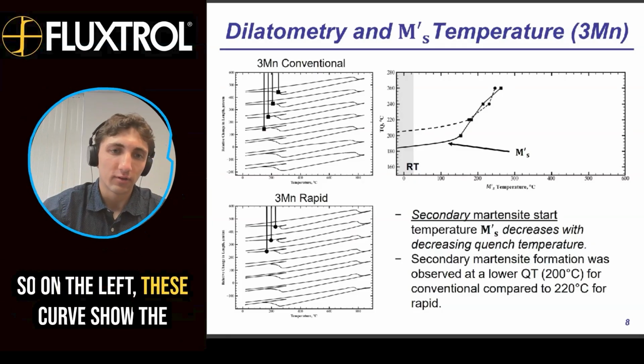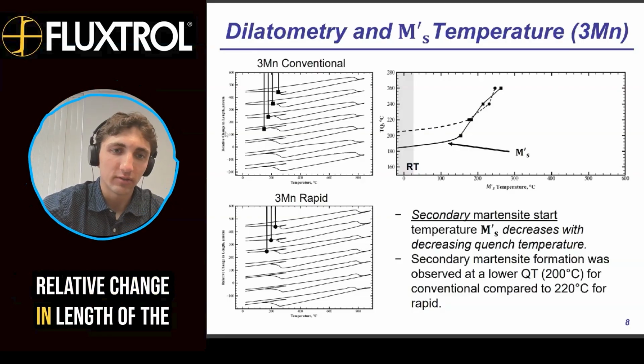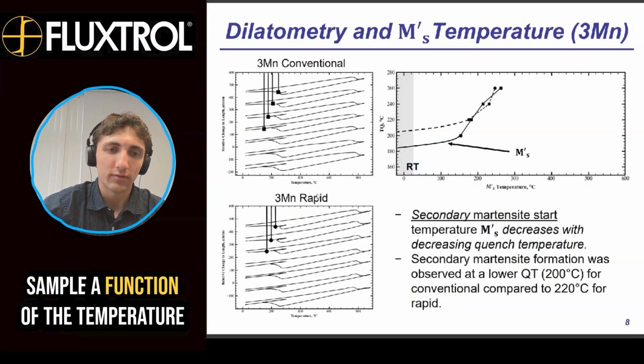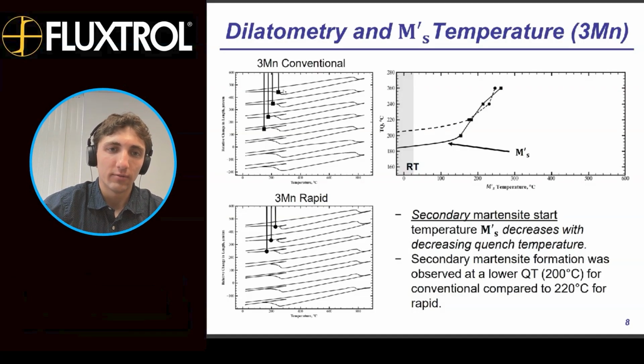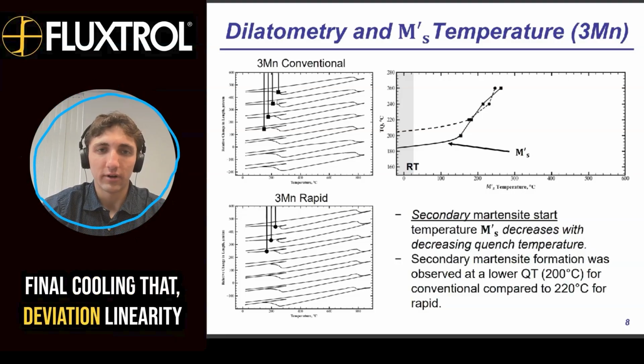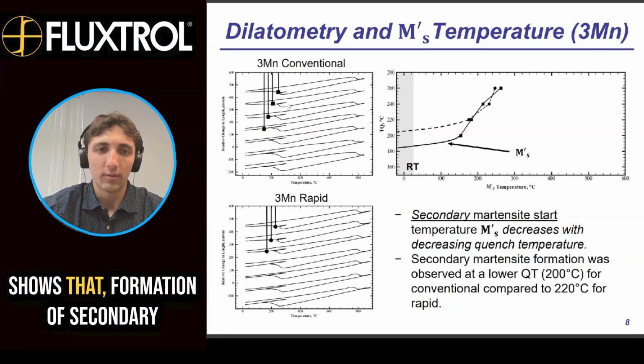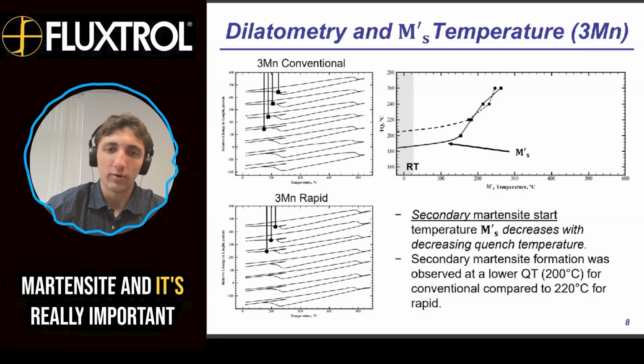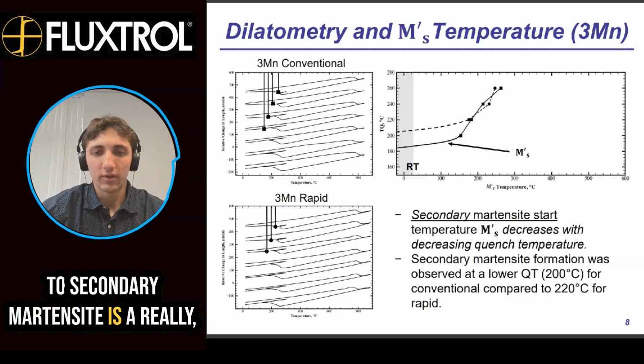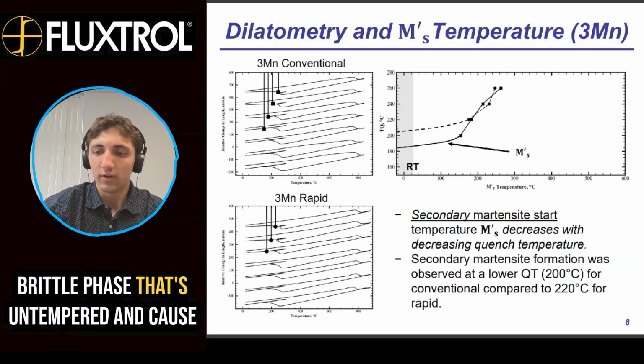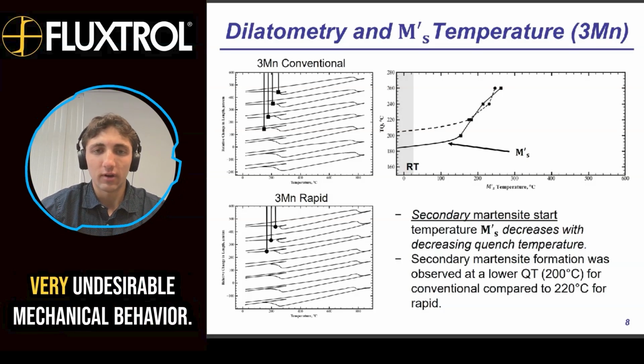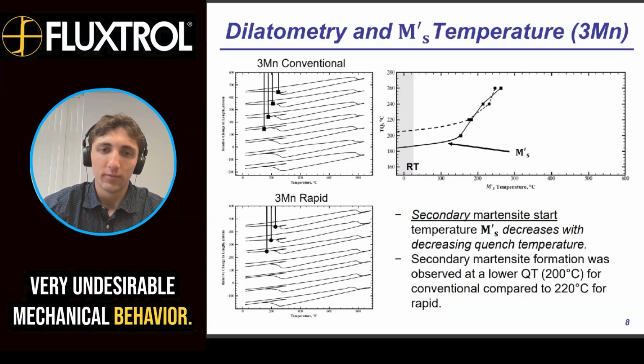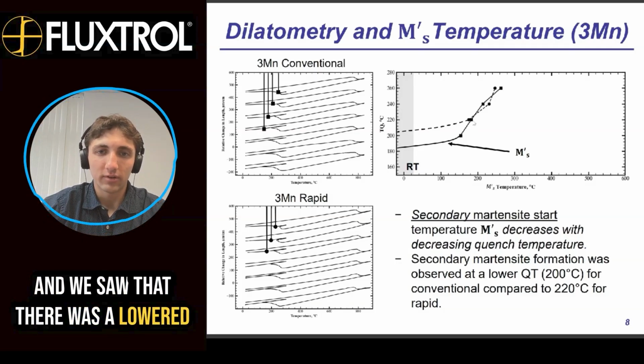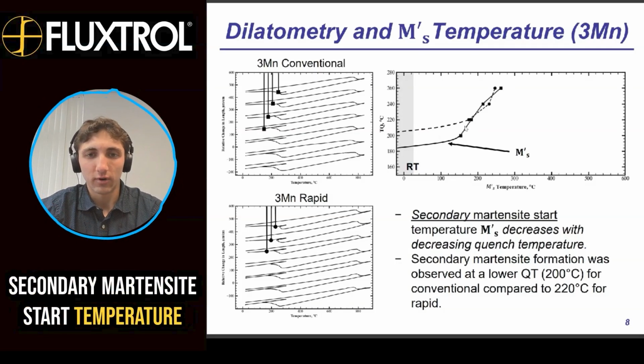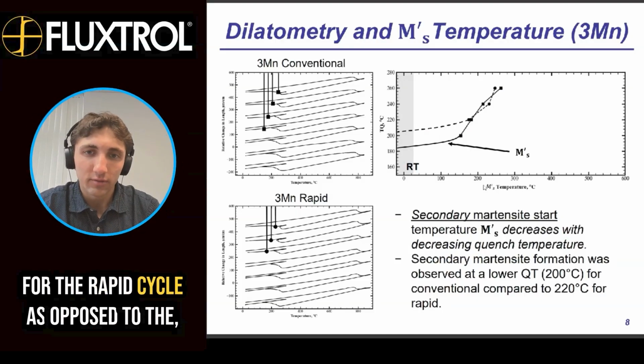So on the left, these curves show the relative change in length of the sample as a function of the temperature during heating. And upon final cooling, that deviation from linearity shows the formation of secondary martensite. And this is really important, as secondary martensite is a really brittle phase that's untempered and causes very undesirable mechanical behavior.